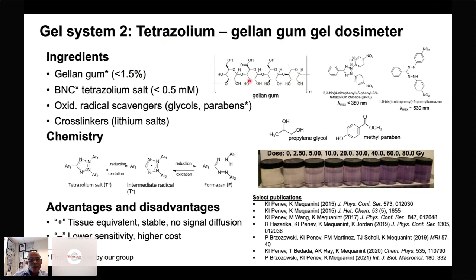So we chose that gel because it forms a stable gel at low concentration, and then we have synthesized, through a very lengthy chemistry, and if you are interested, I invite you to read this paper, which is in the Journal of Heterocyclic Chemistry that we published in 2015. It's a multi-step process to actually get this radiation tracer molecule that can be activated using the clinical range doses. And then we have added a few radical scavengers and some cross-linkers, which is a lithium salt in this case. And we were able to meet most of the criteria that we set at the beginning using this particular hydrogel system. And again, the details are published in these papers, and so I invite you to go and have a look at it if you are interested.